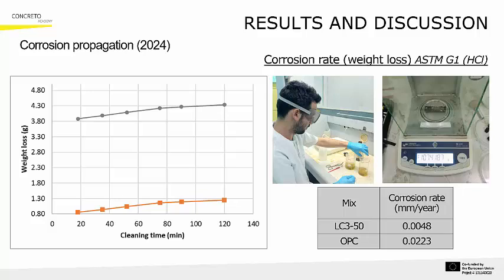Rebars from OPC concrete had lost significantly more mass than those from LC3 concrete. When the actual corrosion rates were calculated, the difference became even clearer. Rebars inside LC3 concrete corroded at a rate approximately 4 times lower than those in OPC after 10 years of marine coastal exposure.